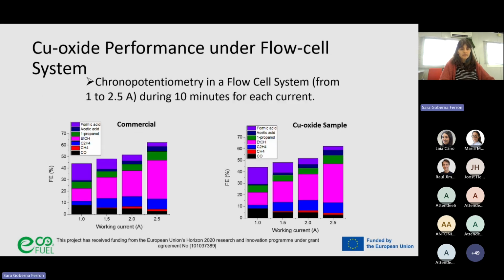So these are the electrochemical results of the catalyst using these flow cell conditions, using a chronopotentiometry from 1 to 2.5 amps. On the left, we show the performance of the commercial reference catalyst, and on the right we show the performance of our copper oxide catalyst. So the bar charts are the Faraday efficiency, and we can see that as the current increases, both catalysts produce mainly liquid products. And in our case, with these conditions and with this flow cell system, we obtain ethanol as the dominant product.